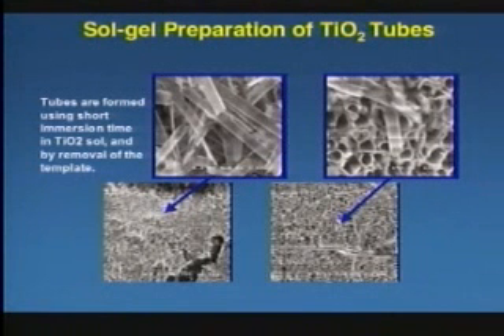But the more important point is when you fill them with either the liquid or the inorganic absorber, the idea is that you can do this at a much lower material purity than you could have done with single crystal silicon, because you spatially separate these two dimensions. And we're trying to do that right now.